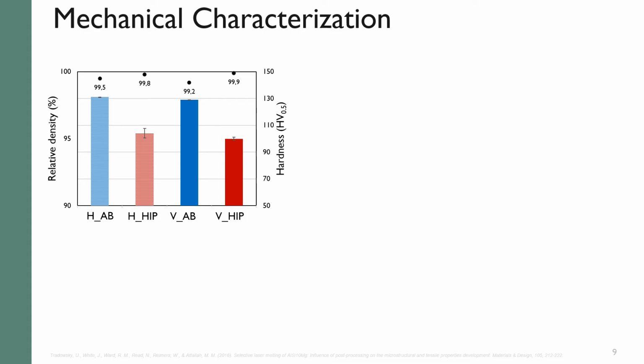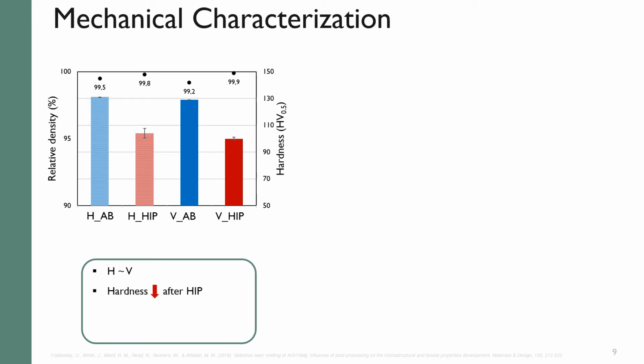Here you can see the relative density and hardness values for horizontal and vertical samples in as-built and HIP condition. While there is no difference in hardness between horizontal and vertical orientation, HIP treatment resulted in much lower hardness values for both.